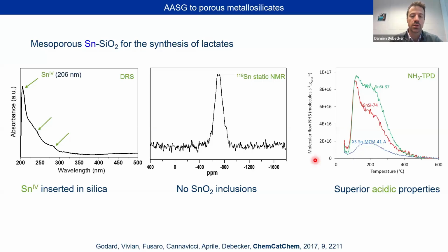What I told you also is that we need the tin to be highly dispersed in the material. And this can be checked by various characterization techniques, like for example here in UV-visible spectroscopy, we see mostly the signal for isolated or dispersed tin inserted into the silica matrix. And in NMR, we also see a signal for tin that allows us to exclude the presence of tin dioxide inclusions.